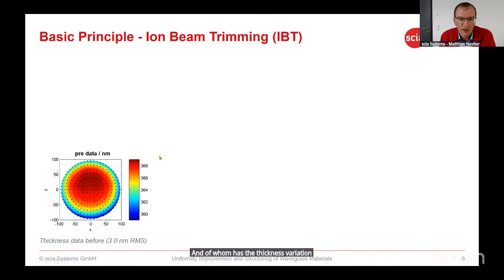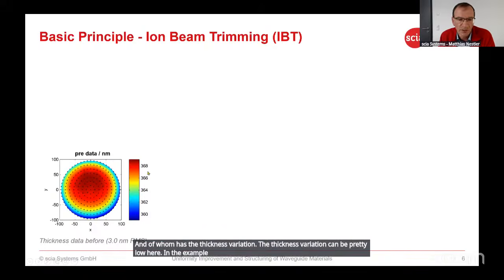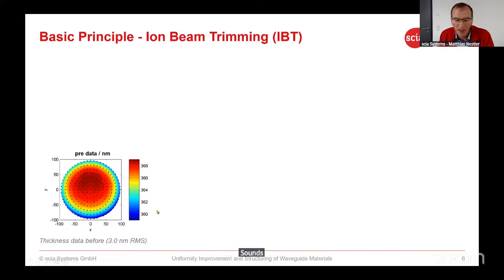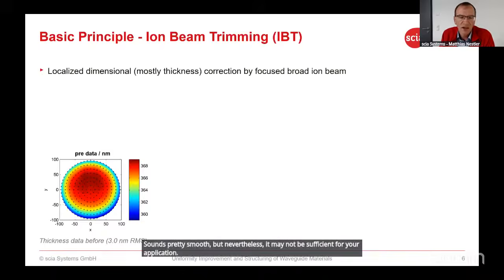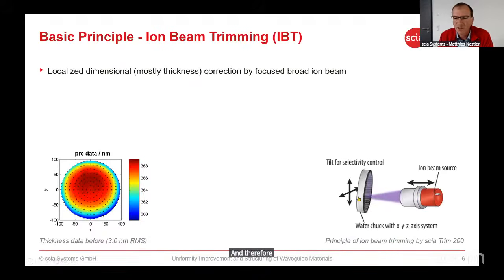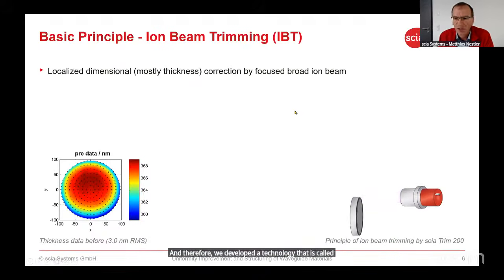The thickness variation can be pretty low. Here in the example, you have a variation from 368 to 360 nanometers, so just 8 nanometers variation. Sounds pretty smooth, but nevertheless, it may not be sufficient for your application. And therefore, we developed the technology that is called ion beam trimming.